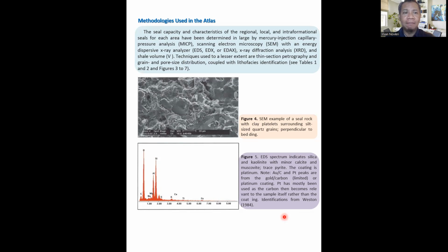So, the interfacial tension refers to the force between mercury and air, while the contact angle represents the angle formed between mercury and the solid surface. In laboratory conditions, the IFT of mercury-air is approximately, as mentioned earlier, 480, and the contact angle with the solid is around 140. This value is used to calculate subsurface capillary pressure for hydrocarbon.